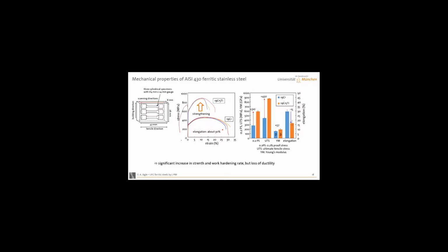I don't need to play tricks with this y-axis here at all. You can immediately see that there is a big difference. Yield strength is going up, UTS is going up. Unfortunately, elongation is going down. Yeah, so we do the usual trading of ductility for strength. But it is quite a significant increase in strength. I mean, it was something.